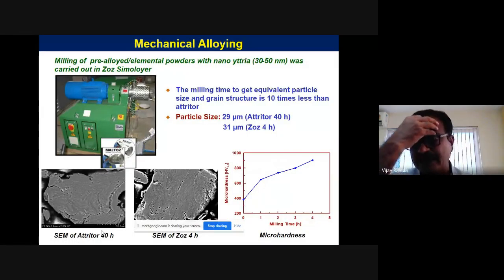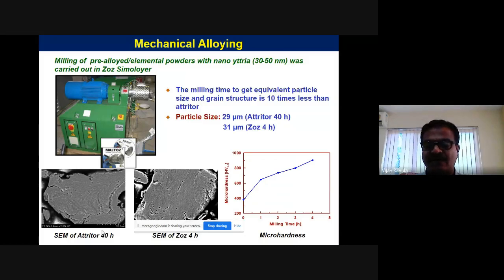And subsequently, for mechanical milling, we use a horizontal high energy ball mill. The typical thing when you're looking at mechanical milling is a repeated fracture and welding process taking place because of the ball to ball collisions, and collisions between the ball and the vessel of the mill. Everything depends upon the relative velocity of the balls being generated. If you compare the same material milled in a conventional attritor, it takes 40 hours to give you a particle size and the cell size, but the same thing takes only 4 hours. So the time required for milling when you use this mill is very, very low.